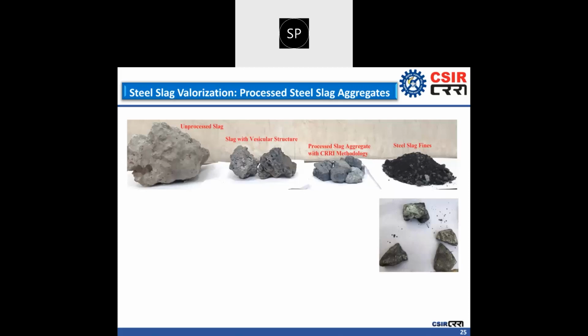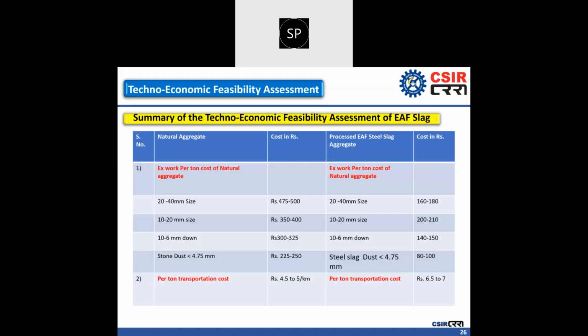And this is the benefit of this conversion process in the form of a costing aspect. The slag aggregate of 20 to 40 size is available between 160 to 180 rupees per ton. This is the cost analysis of EAF slag aggregate carried out for the Hazira, Surat ArcelorMittal Nippon Steel plant. For 10 to 20 size aggregate, it will be between 200 to 210.